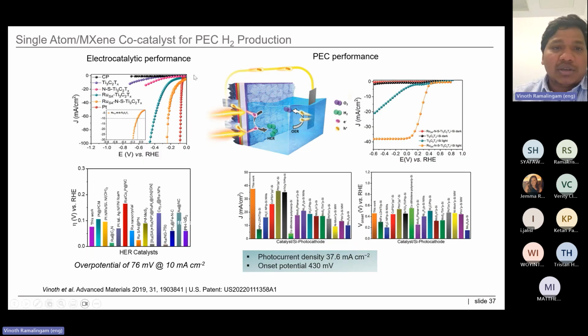First, we evaluated the electrochemical performance, and it shows better performance. And this is our catalyst performance compared to the state-of-the-art systems from the literature. And then we integrated this catalyst. You see, this is our catalyst schematic image. We integrated this catalyst with the p+n n+ silicon photoelectrodes, and it shows better PEC performance in terms of current density as well as the onset potential. And this is the comparison that we made with the existing literature reports.